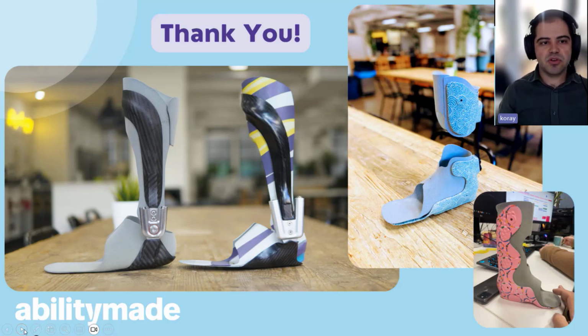Essentially it's great with containment of soft tissue, and you can get the firmness that you need with lattices and the change in thicknesses. So TPU is a really amazing material where if you just add a little, it really goes from being a 2D material to a 3D material. Going from 1.5 millimeters to 2.5 millimeters, it really changes in properties because of how it's built, and can get rigid really quickly. So it's still stiff enough and can be made stiff enough to hold tissue, but still has some flexibility in it as well, even in the stiffer parts. So it's also a very forgiving material.